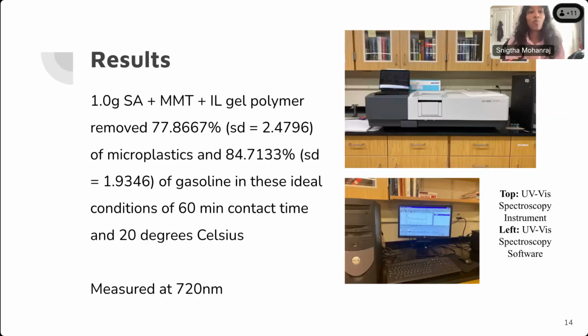So the data showed that 1.0 grams, which is a higher concentration of sodium alginate, along with the MMT and the IL added in, created the most effective gel polymer, removing about 78% of microplastics and about 85% of gasoline. I tested two different contact times, 30 minutes and 60 minutes, and 60 minutes was more favorable. And then I did research at 20 degrees Celsius and 40 degrees Celsius.